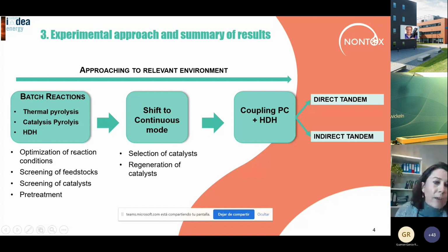Then, after some of these conditions and feedstocks were selected, we moved to operate in a continuous mode, screening a selected number of catalysts, and also evaluating the possibility of regenerating the catalyst. And once all these points were determined, we moved to a final step in which we tried to couple both catalytic pyrolysis and HDH reactions in order to evaluate the final product, this oil, the content of halogens in the oils, and the composition in terms of the content of valuable compounds.